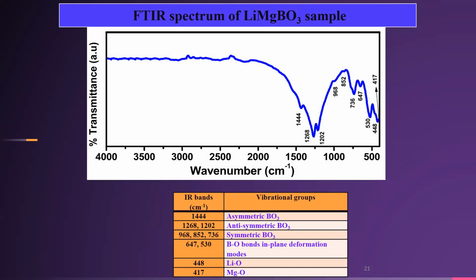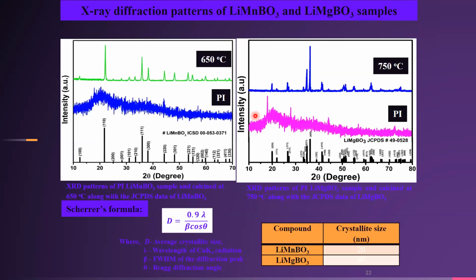And all the observed IR band positions are in good agreement with the reported literature values. It also confirms the formation of lithium magnesium boroxide samples. And the XRD in this figure shows the polymeric intermediate sample. First we can see the lithium manganese boroxide sample, then the lithium magnesium boroxide sample.